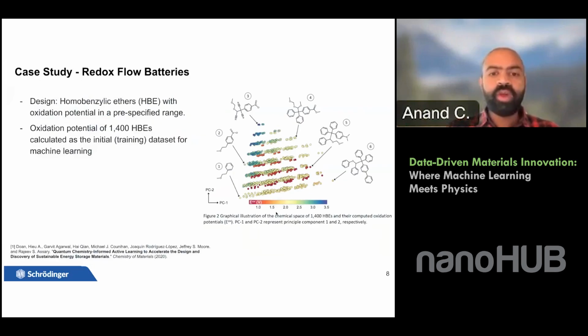So here is a quick comparison of AutoQSAR versus DeepAutoQSAR using a particular case study. This data set was actually generated by a colleague of mine, Garvit Agrawal, at Schrodinger. It is a data set of 1,400 homobenzylic ethers, and these molecules were used as potential candidates for redox flow batteries. One of the criteria for a redox flow battery is the oxidation potential. So we wanted to create a model for the oxidation potentials for this class of materials, so that we can screen a larger number of molecules using the machine learning model as opposed to using DFT.